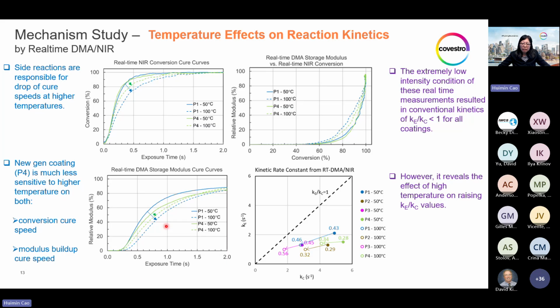It is not a surprise that at high temperature, both the conversion and the modulus buildup rate will decrease. You can see the arrow pointing down from 50 to 100 degrees C, because the side reactions are occurring more at the high temperature. What's special is the new generation coating P4, which is this green arrow, decreases much less than the conventional coating P1, the blue arrow. This means the new generation coating is less sensitive to the temperature. However, when plotting the modulus versus conversion, the P4 is in the exact same shape as the P1, still showing the classic shape of accelerated increase.